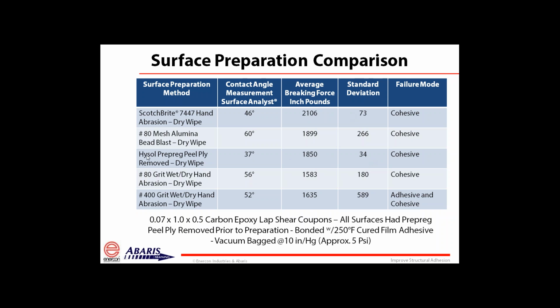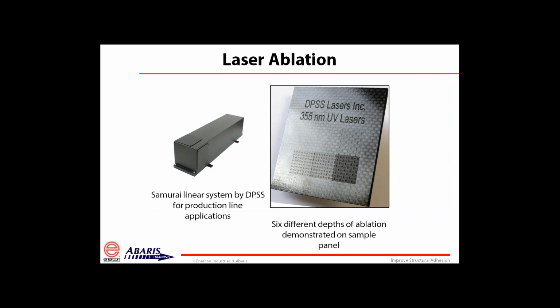Now, of course, abrasion techniques may or may not apply in your facility, and therefore you may be looking at this webinar today to learn more about the application of plasma. One other method of abrasion, however, is laser ablation, and it's actually an ablative method because that's the method that the laser uses to remove the matrix on the surface. You can see here's a panel done by DPSS Lasers Inc. They provided a panel to me where they did 6 different levels of ablation to the surface.